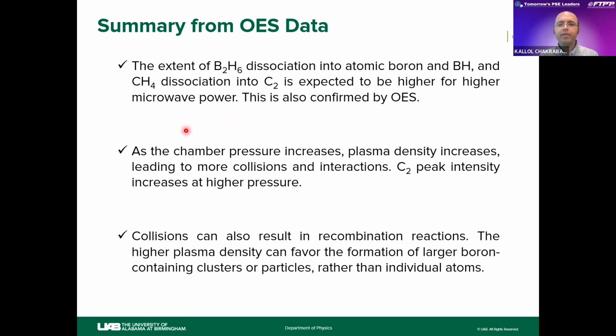As the chamber pressure increases, the plasma density also increases, leading to more collisions, and due to this collision, we get more C2 peak in the plasma. The collision can also result in the recombination process. The higher plasma density can favor the formation of larger boron-containing clusters or particles rather than individual atoms such as atomic boron or BH. For this reason, when we increase the pressure, the atomic boron peak intensity decreases. Maybe we are forming larger boron particles, but optical emission spectroscopy can only detect the excited species, so we are not able to see it in the plasma.